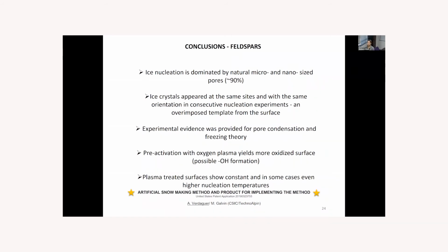Pre-activation with oxygen plasma yielded more oxidized surfaces with possible OH formation, and this allowed for higher nucleation temperatures and constant nucleation temperatures. And most importantly, based on these works on feldspar, all the investigation we've done, Albert and TecnoAlpin have issued a patent for artificial snowmaking method and product for implementing this method. So it was quite successful work from our part.